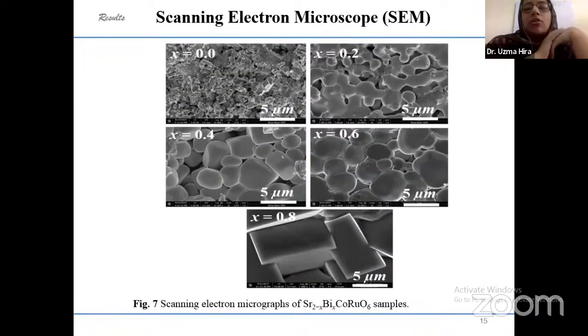So these are the scanning electron microscope images for this material. As you can see, the grain size is continuously increasing with increasing bismuth content. It means the melting point of the bismuth-containing constituents is lower than that of strontium carbonate, which results in bigger grain size development with increasing dopant.